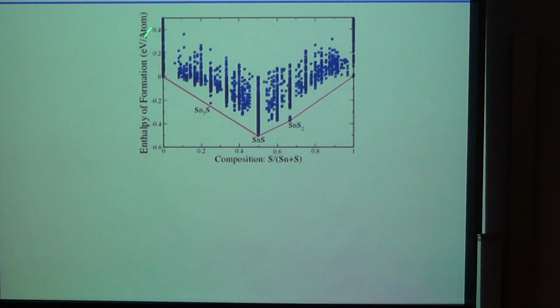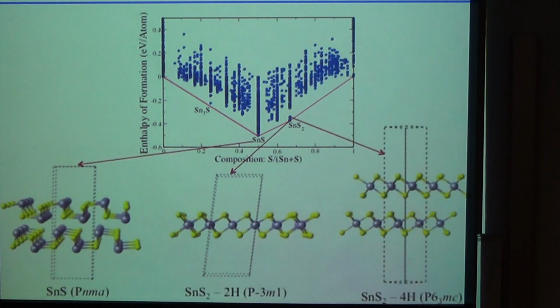And as I said, this is a particular example of the tin-sulfur compounds. We see some different stoichiometries, and we look at the structures, and then what we do, we characterize the structures by calculating different properties: electronic, vibrational, optical, and so on and so forth. So this is how it works in the case of tin and sulfur. We look at the lowest one, this 1,1 stoichiometry, we get this one. This is known, by the way. The key thing is that we don't use experimental information; this is how we test that our calculations work. We predict known compounds. It's an important test, okay?